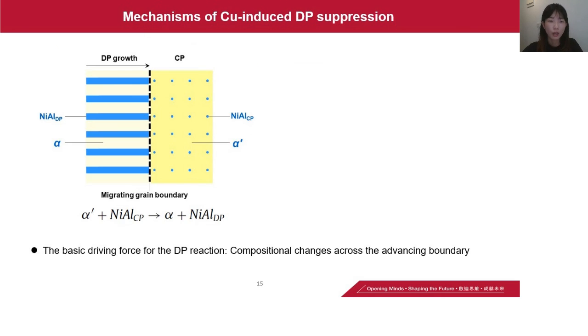For the mechanisms of copper-induced DP suppression, the precipitation behavior can be schematically illustrated in this figure. The left side is the V-shaped discontinuous precipitate and the alpha prime phase with the higher supersaturation, and the right side is the continuous spherical nickel-aluminum particles and the alpha prime phase with a lower supersaturation.